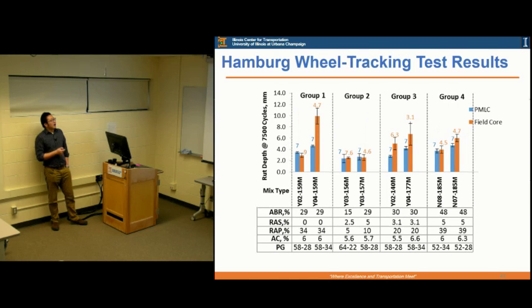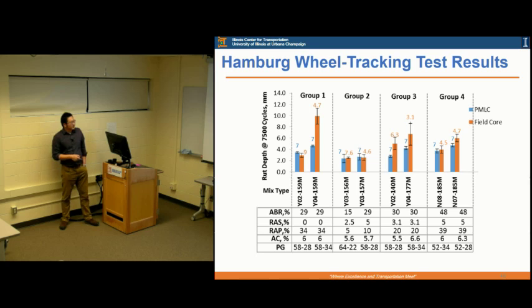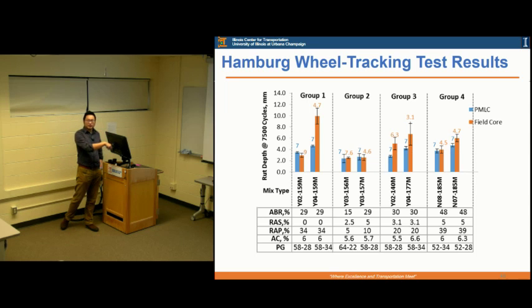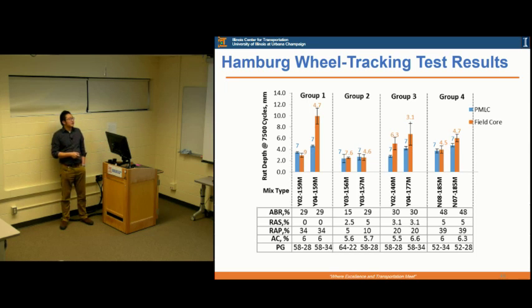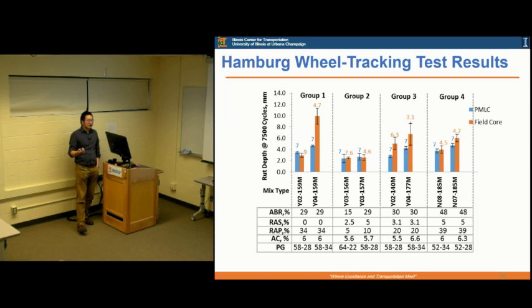This is the Hamburg wheel tracking test results. We're using the rut depth at 7,500 cycles, and what you can see is that for some mixes, the field core had a higher rut depth than the one in the lab. Similar trend - the field core tends to be softer than the mixes in the lab. But some mixes are pretty close - for example, for group 2, they're pretty comparable. But for other mixes, the field core is softer than the one in the lab.